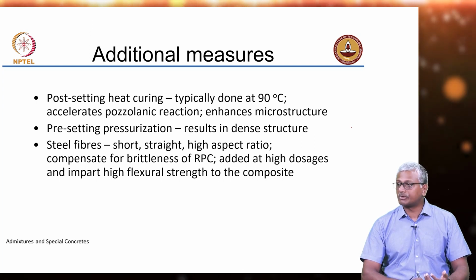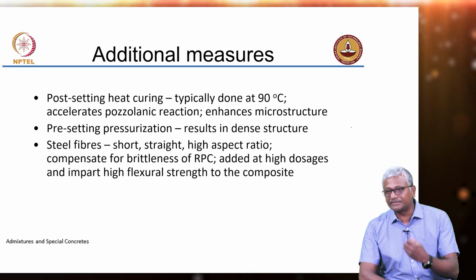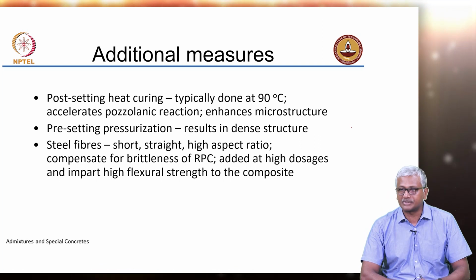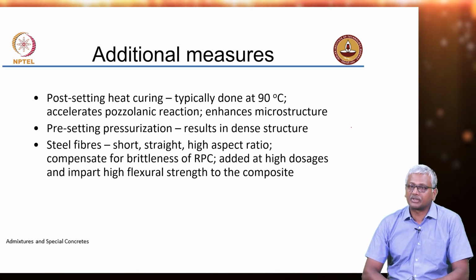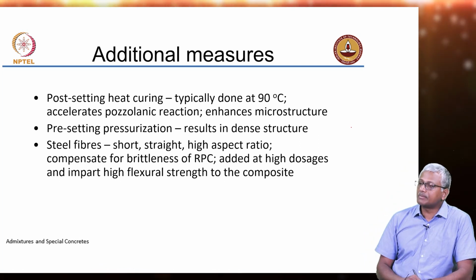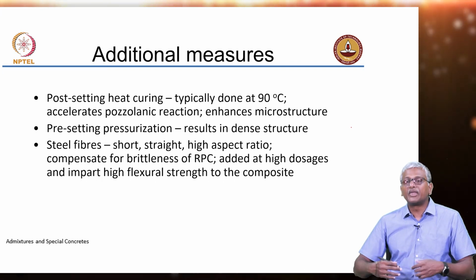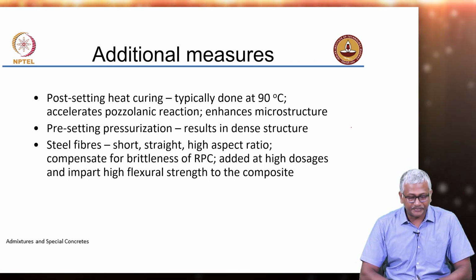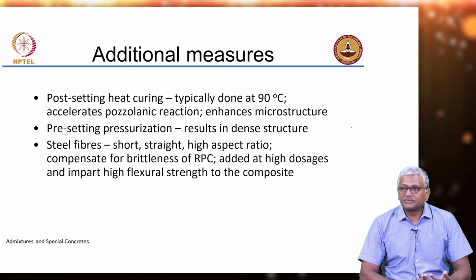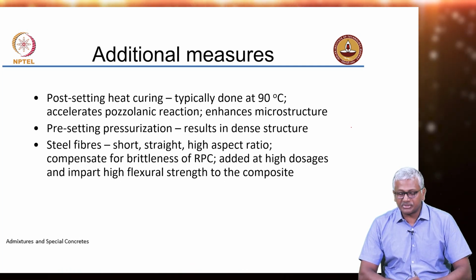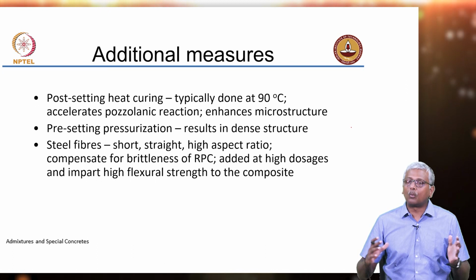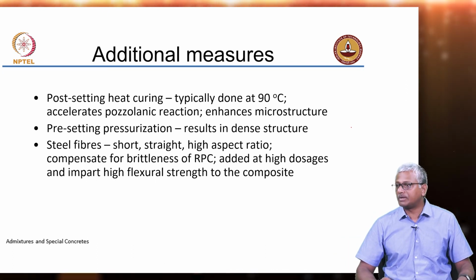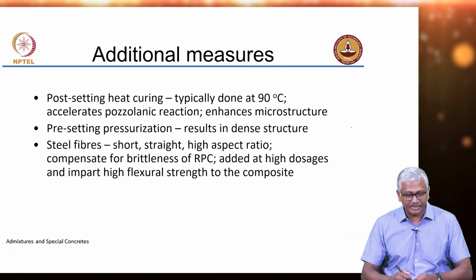It accelerates the pozzolanic reaction, it makes silica fume contribute something at the early stages, and also enhances microstructure. You are further increasing the rate of cement reaction. Whatever hydration takes place now takes place much faster. The other strategy which we discussed earlier, presetting pressurization. So, you do not allow voids to form and compact the concrete while it is setting. So, it results in a dense structure.